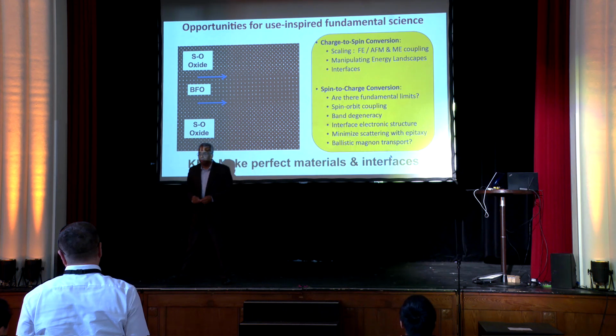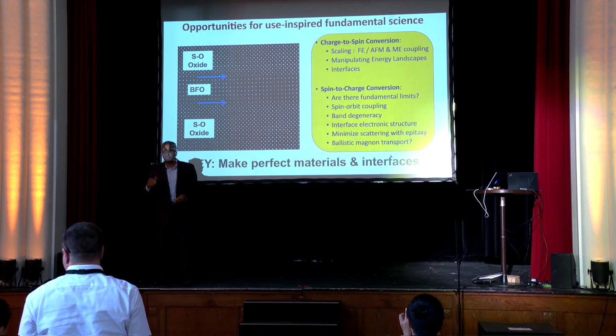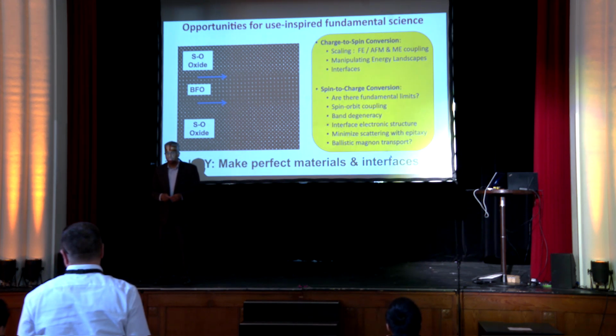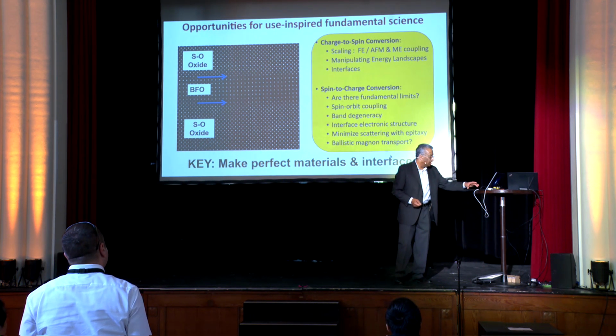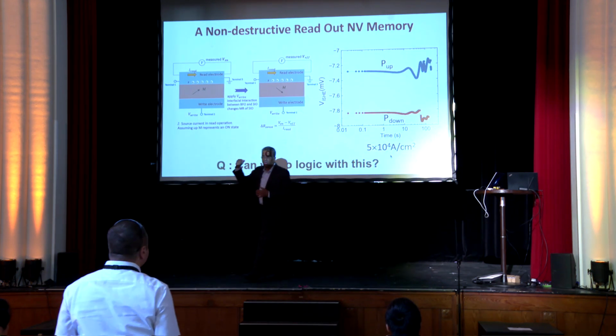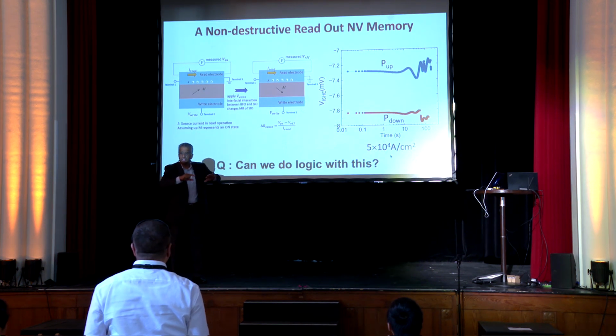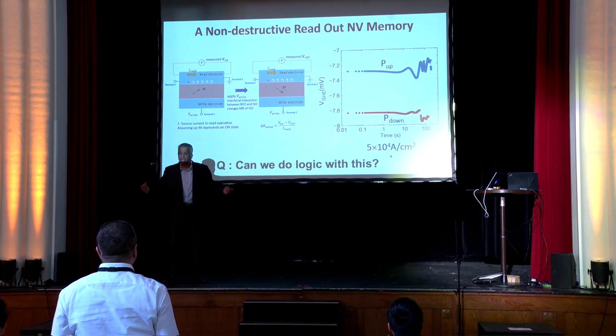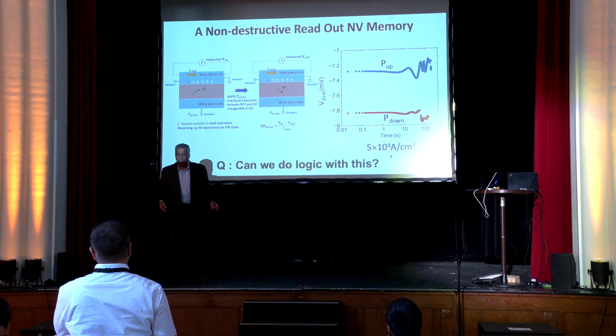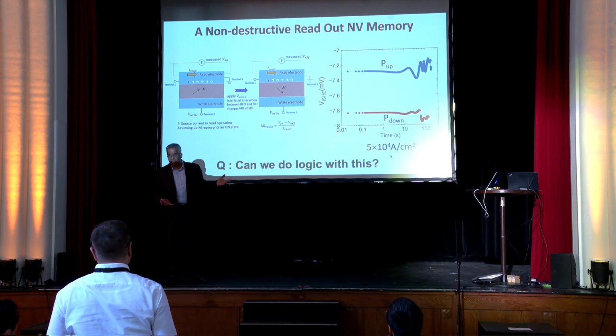The ferroelectric part is at least 3 orders of magnitude more advanced. There are startup companies, advanced companies which are doing it. But doing the spin part and the charge part together is not trivial. It's only going to work if you have the ability to get very large output voltages. Now, if you look at the MESO structure, there was a ferromagnet. In this structure, there is no ferromagnet. We got rid of it because you're now reading out the antiferromagnet directly. And that's relatively new. Actually, we are seriously thinking of doing a startup company on this because we think we can get to these kinds of numbers. We've still got some work to do.